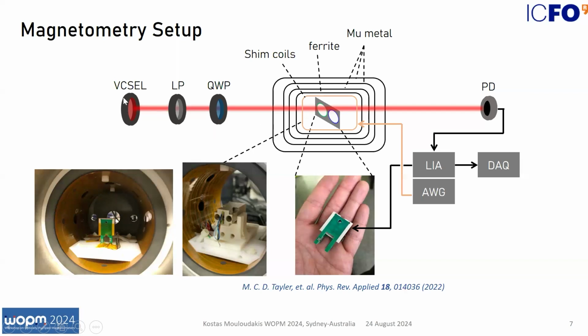And then we use a high power VCSEL laser of 1 milliwatt and some optics to polarize the beam. Then we use a commercial lock-in amplifier to modulate the transverse magnetic field, and we demodulate the optical transmission. And the output of the lock-in goes to a data acquisition system, and we also use function generators to produce test signals to test our sensors.